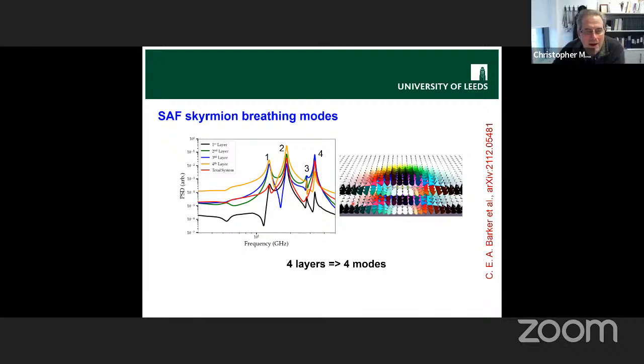in the spectrum. But what is interesting is that individual layers can be oscillating quite strongly, whereas the net effect may be quite weak sometimes. But sometimes the net effect is quite strong, so maybe these first and second peaks, there's quite a bit to see. So this could be a way to detect Skyrmions, because in these antiferromagnets, it's hard to see what's happening because there's no net magnetization. So a lot of the imaging techniques that you might try and use to see a Skyrmion won't work. But you could excite your material at high frequency, and if you see a peak, then you might know that Skyrmions are there.